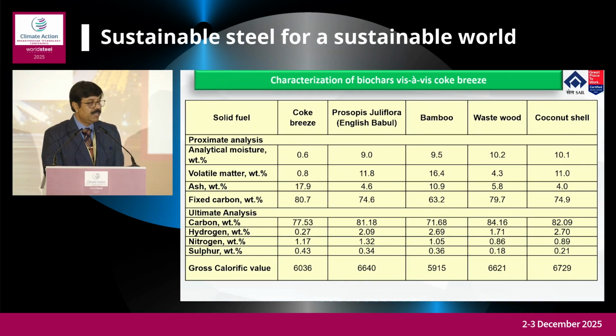This is the proximate analysis of that biochar versus coke breeze. We have shown that in the first column it is coke breeze, and the proximate analysis data is like that. If you come down to the last row, gross calorific value, the coke breeze has 6,000, and as against that, the bamboo biochar we have chosen for the alternate use is 5,900 or, say, 6,000. So, it is almost equivalent to the coke breeze.